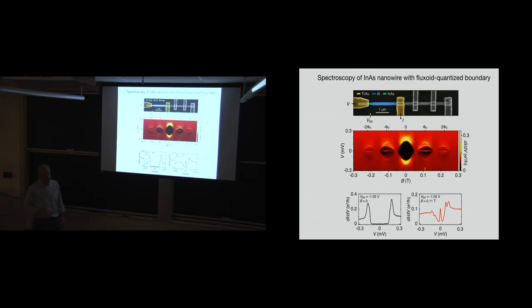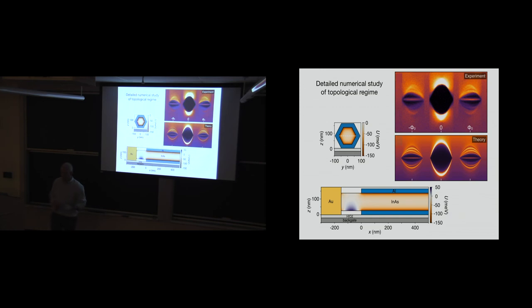So this was a pretty surprising discovery. Well, maybe not, now that I've kind of walked you down the garden path to it's a vortex in a material that has strong spin orbit coupling that would create a Majorana zero mode. Maybe it's not so surprising. But it was kind of nice when our numerics friends actually modeled the system, put all the thicknesses in, made a very detailed model, including the dielectric and the gold and all of that stuff, and the theory plot ends up looking pretty much like what you'd expect, with a trivial superconductor in the zeroth lobe and a trivial superconductor with one extra zero bias state in the first lobe.